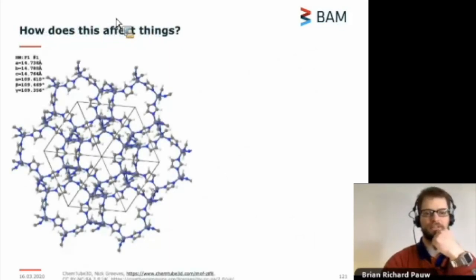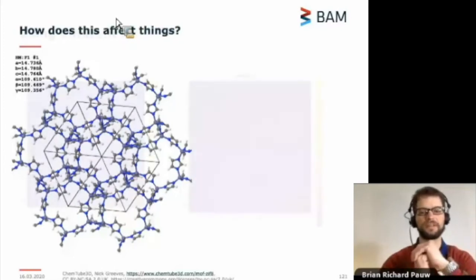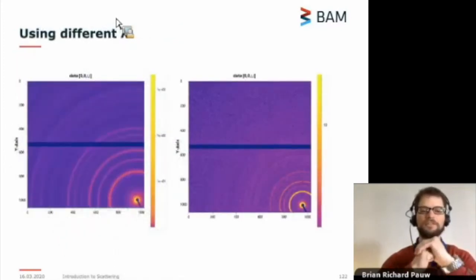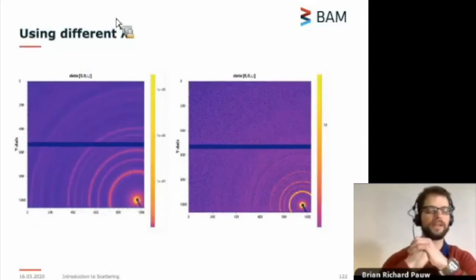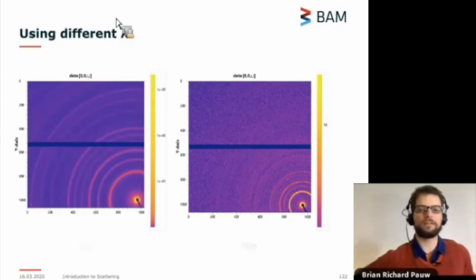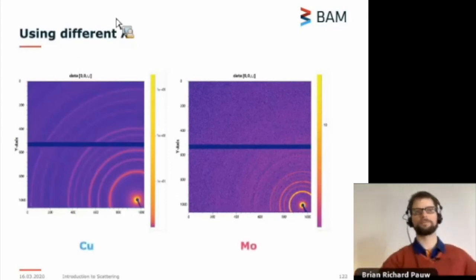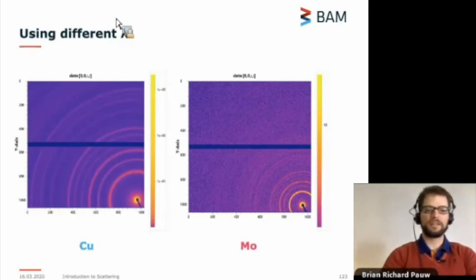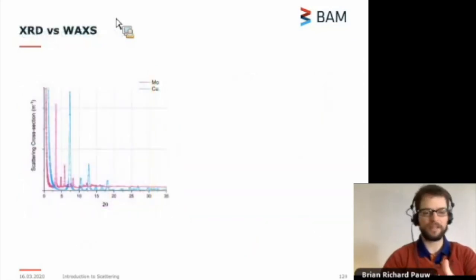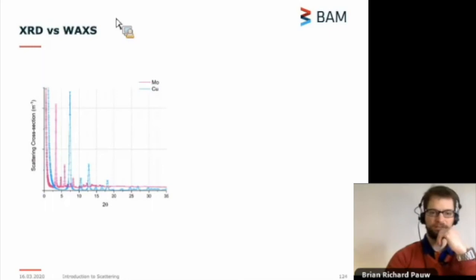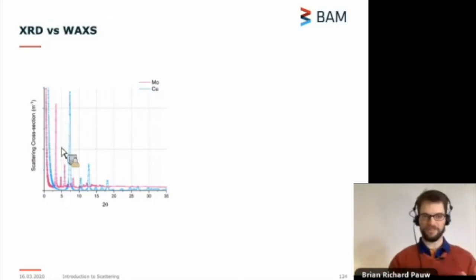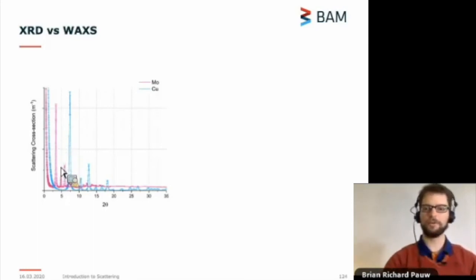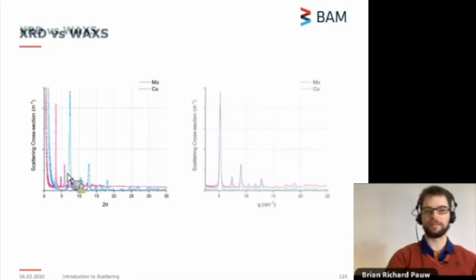So this ZIF-8 structure was also measured with different energies, two different sources, detector at the same distance. You see that the diffraction rings that were visible in copper to fairly wide angles are now suddenly scrunched together and are much closer to the beam stop with our molybdenum source. If you would look at this in XRD, the peaks would be in different places because the angles in 2 theta are different. However, the peaks are still related to the same crystalline structure. So when we show this in Q, we actually see that all the peaks are in the same place.